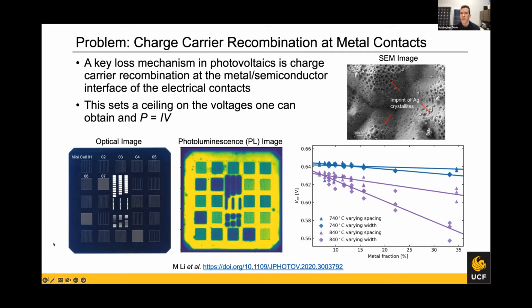So that's a problem. And then we can show why that is the case. When you tend to get a lot of silver crystallites forming that punch into the silicon, that becomes an issue. So that's one of the big problems right now that establishes a ceiling on where these devices can go.